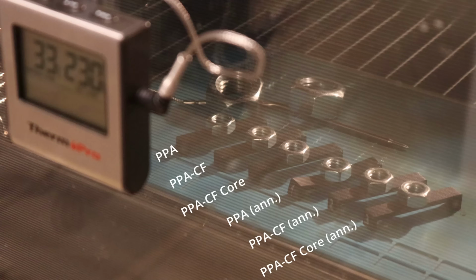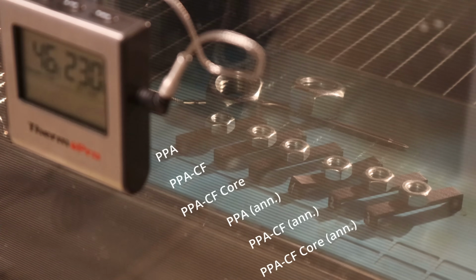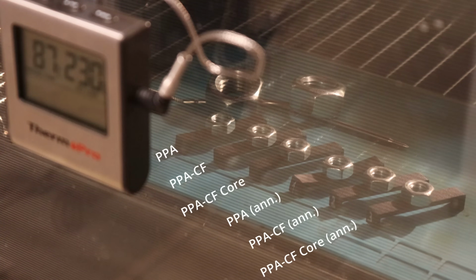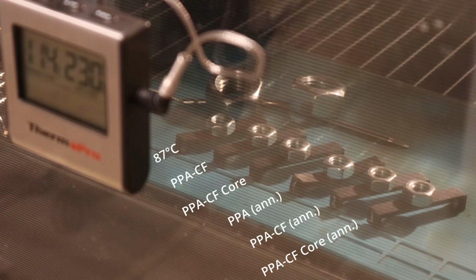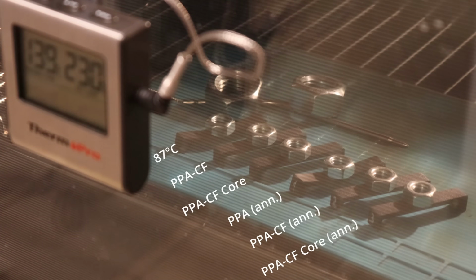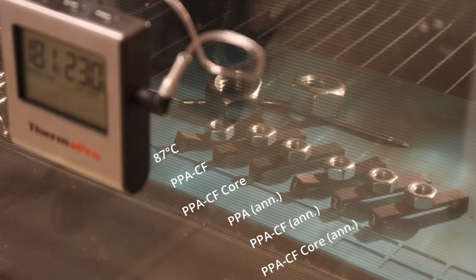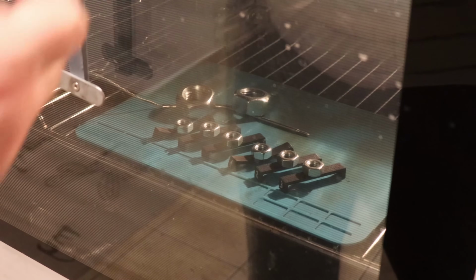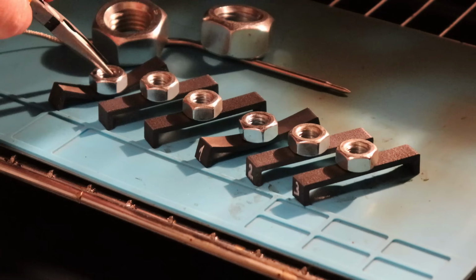This is speed up time-lapse video, and I thought nothing will happen until near 200 degrees Celsius, but the PPA started to deform quite early, at approximately 87 degrees Celsius. After this it slowed down, but later it continued with deformation. And then I have here jump in the time. And the next one was the PPA annealed version, which started to deform at approximately 199 degrees Celsius. And after this I stopped the experiment on 220 degrees to see how hard are the rest carbon fiber filaments.